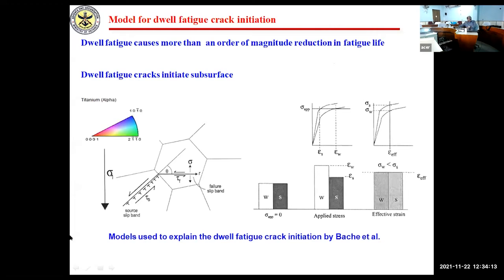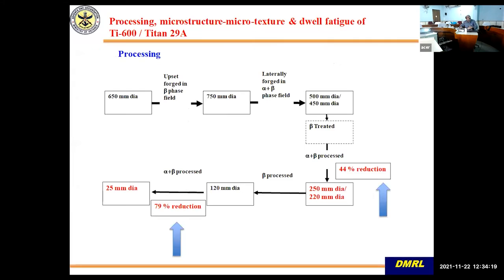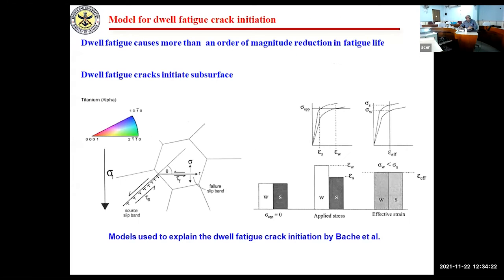Now, what happens is, as compared to fatigue, as I told you, in dwell fatigue, you hold a load for a certain amount of time at the highest stress, and then the crack forms. Now, there has been an explanation given by Bache et al., which still holds good, although a lot of research is going on in this. The other thing about dwell fatigue is that it causes an order of magnitude reduction in fatigue life.